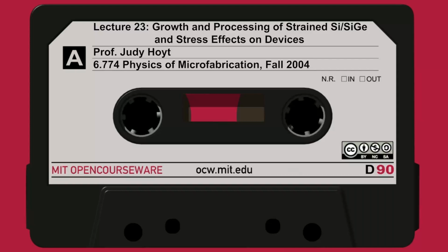So they start with a wafer you buy from a commercial vendor with a silicon on insulator. They epitaxially grow a thin layer of silicon germanium with a relatively low germanium content, and then they oxidize the whole thing. And it turns out in the oxidation, the germanium is snowplowed forward into the layer, and the layer relaxes. So they end up with a higher germanium content after oxidation, and the originally strained silicon germanium layer ends up relaxing by the oxidation process at very high temperatures. So that seems to be interesting.